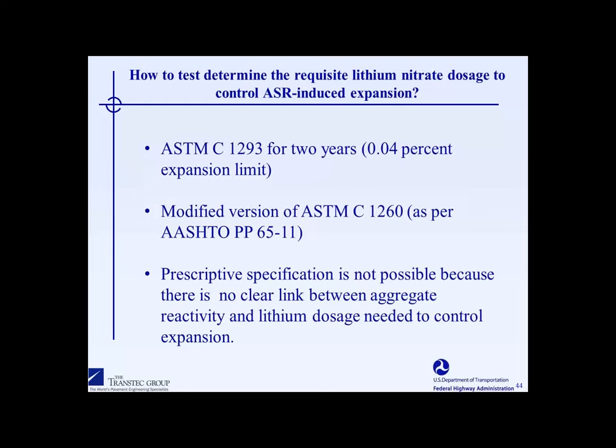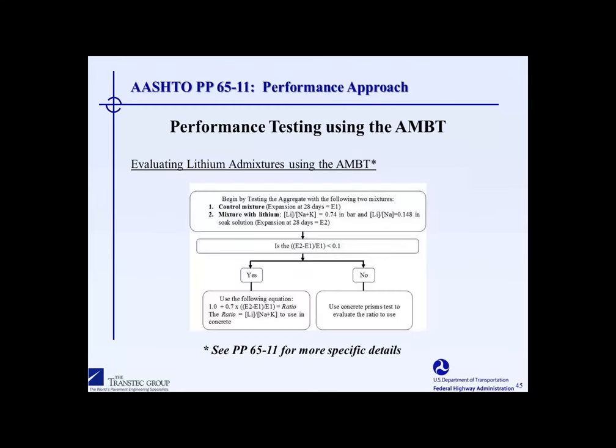One point should be made here: we do not have the ability to prescribe the amount of lithium needed to control a given aggregate, because there's not a very clear link between how reactive an aggregate is in terms of its expansion level in the concrete prism test, for instance, and the amount of lithium that's needed. So the only way to determine how much lithium is needed is to do performance testing. I mentioned that the accelerated mortar bar test can be modified for testing lithium. I'm not going to go into it in detail here, and I'm just showing a snapshot of a flowchart that can be used following the AASHTO protocol.